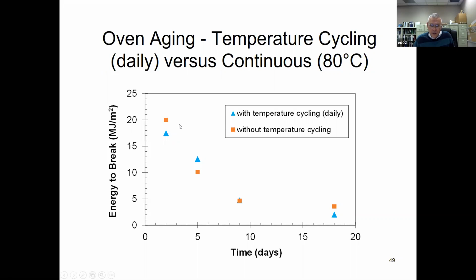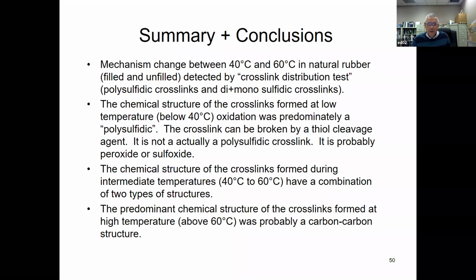So we said this idea didn't work. I mean, that wasn't a valid idea. Okay, so in summary and conclusion of this second half, we say there is a mechanism change between 40 and 60 degrees in natural rubber. And I would say in most other elastomer compounds, it's stronger and easier to detect, but it was very elusive and hard to detect with natural rubber.